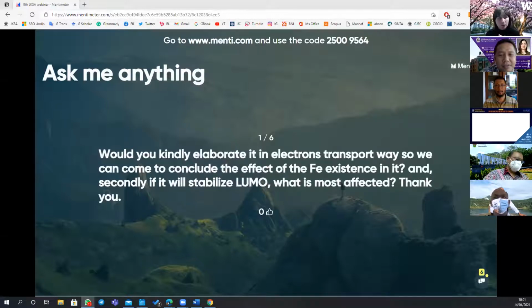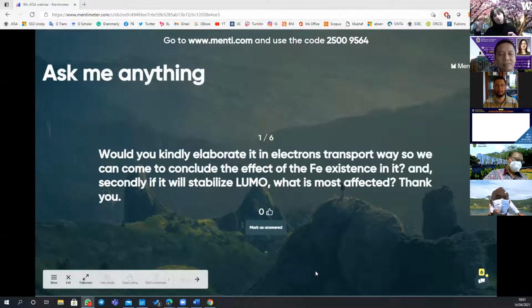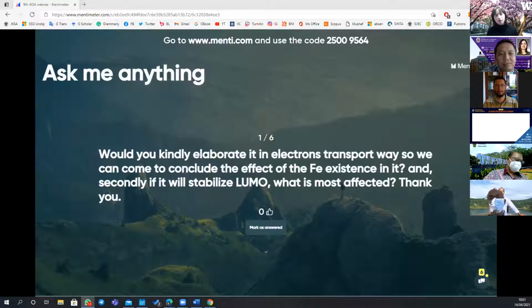And so we do think a lot about electronic transport through the material, like in bulk. But most of these, because they are separated by the organic ligand shell, are not conductive cluster to cluster to cluster. So while we can cycle through different oxidation states within the cluster itself, we have not yet solved this problem of how you connect the clusters together, which is an important problem to solve. How do you connect the clusters together in a way that they communicate, and now you have like a wire or something like that. So they're not conductive in that sense.